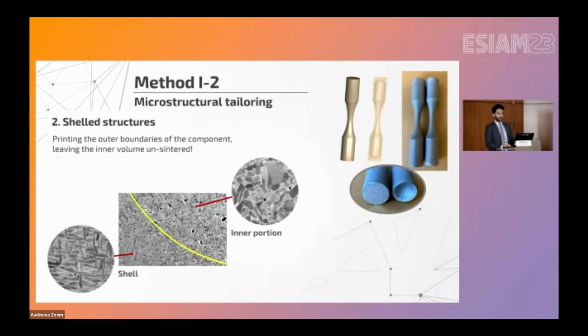We could see, okay, around the shell, after annealing, we had the basket weave microstructure with quite thin alpha grains. Going towards the inner parts, we had more of an equiaxed microstructure for this titanium sample. And the grain even got coarser when it was in the middle of the sample. We had a challenge because we didn't,